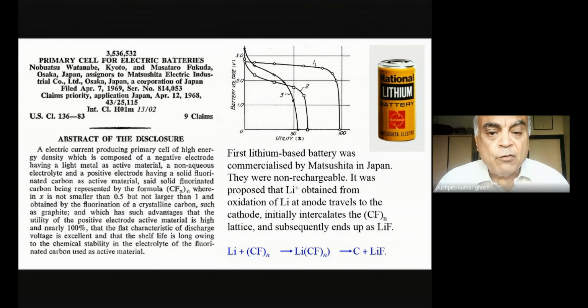So what they did was a very interesting construction of the cell. They took lithium metal as the anode. They had an organic solvent in which they were able to find certain electrolytes which would dissolve in that organic solvent. And at the cathode, what they did was very interesting. They took graphite, which is used conventionally as an electrode material, but that's not what they did. They fluorinated the graphite, so they made it something like CFn.